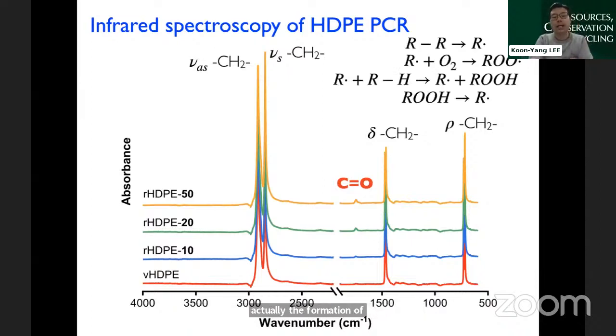And this is because when polyethylene gets run through an extruder, at high temperature, loads of interesting things happen. So the bonds between your carbon-carbon bonds can get broken just through simply thermal degradation or shear. So once that carbon-carbon bond breaks, you form a radical. So that's R dot, alkyl radical. And in the presence of oxygen, which we do have, it actually reacts with it and forms another radical.